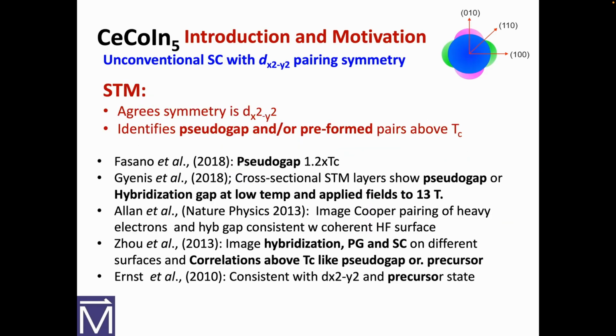So here's a list of papers that I actually reread again this year, which are really great papers. The STM agree, except if you get Seamus in the corner of one of the rooms, he'll say, well, maybe not, but pretty much everyone agrees it's dx squared minus y squared. And the STM all agree that there's something going on above TC. These papers, which I probably haven't listed them all, are all worth reading. They all claim that there's something going on above TC. There are arguments that it's preformed pairs in certain directions, hybridization gaps in other directions.